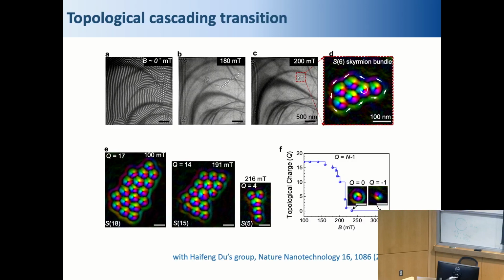But also the first A, B, C are measurements, and the D, the color, is that a measurement or is that a simulation? This is a measurement. So this is the so-called Lorentz TEM, TIE something. Okay. So you already have a spin direction for each location. Right. So this color stands for the in-plane spin directions. This is done at room temperature. This is low temperature. This is iron germanium. Iron germanium has a 288 Kelvin transition temperature.